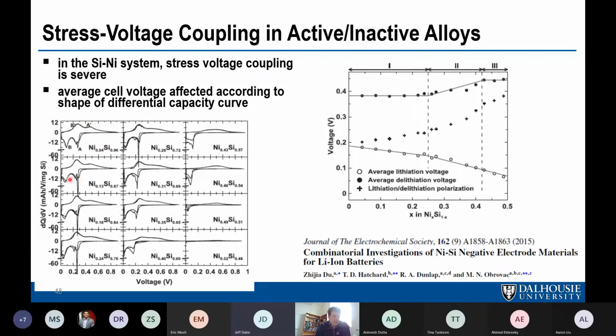If you keep adding nickel, you can see the lithiation voltage is shifting, and it keeps shifting to very low potential. And that's graphed here. And there's 3 regions. In the first region, as you add nickel, nothing much is happening until you start chewing away at this peak. And if you start chewing away at this peak, then the corresponding peak in the charge curve is going to start to go down, and that's going to affect the average potential during delithiation. So during the initial shift, nothing much happens. You're not reducing the capacity much.